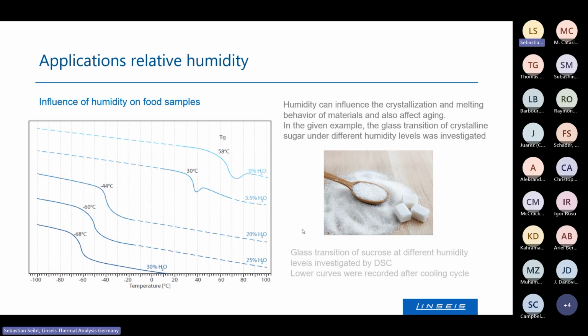High humidity level, first of course, then freezing the sample, and then again heating it up led to a shift of the glass transition down to more negative temperatures, from -44 to -68 centigrade.